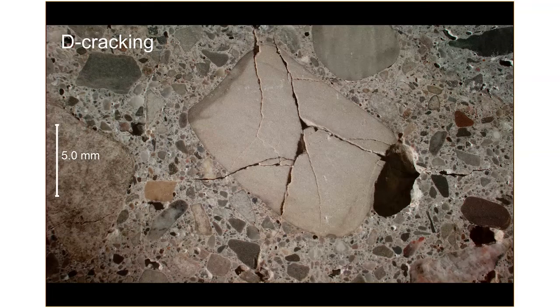Now, this concrete is not without problems. There is certainly freeze thaw seen at the joints. It is seen freeze thaw of the aggregates, and the Minnesota Department of Transportation and Iowa and Ohio and just about anywhere that uses limestone aggregate, or used to use limestone aggregate in their concrete, has been vetting carbonate aggregates for many years. There's a certain number of carbonate aggregates that will break down after 5, 10, or 15 years. They break the concrete down because the aggregate is generally a dolomite, which is more porous than a limestone, and it is not freeze thaw resistant.